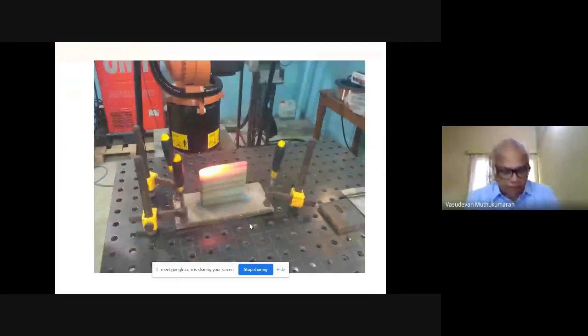And moving on to laser welding. We especially use laser welding for end cap welding. This is a fuel element with uranium oxide pellets loaded inside. On the sides of the tube, we need to weld end plugs. Earlier we were using TIG welding. We have now moved on to pulse laser welding. You can see in the lab we developed the technology.